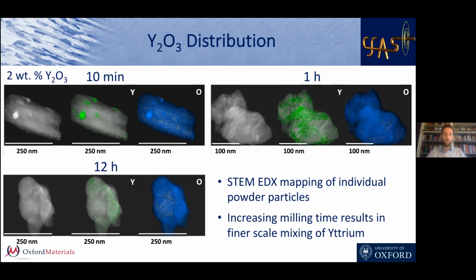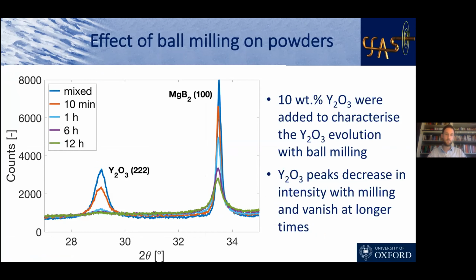And as we increase the milling time, they slowly dissolve in the particles. And that is also observed in steel and superalloys, where we see the yttrium oxide dissolving in the matrix. Again, if we take some XRD results to confirm that, we saw that after 6 and 12 hours of milling, the yttria peak completely disappeared, which also confirmed that probably the particles dissolve in the matrix. So that's a really good result, because the first step of an ODS process is to first dissolve it in the matrix, and then you want to make it precipitate in a controlled fashion, to have the good properties of that small dispersion.